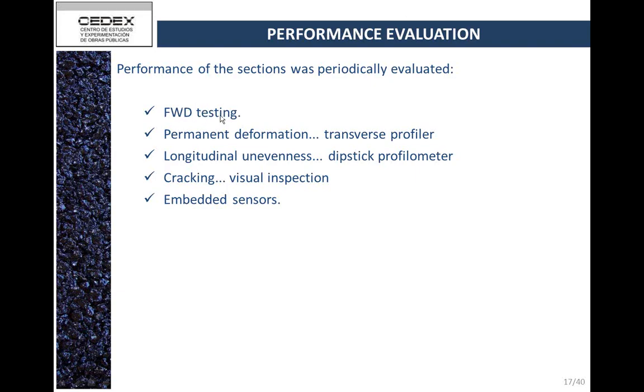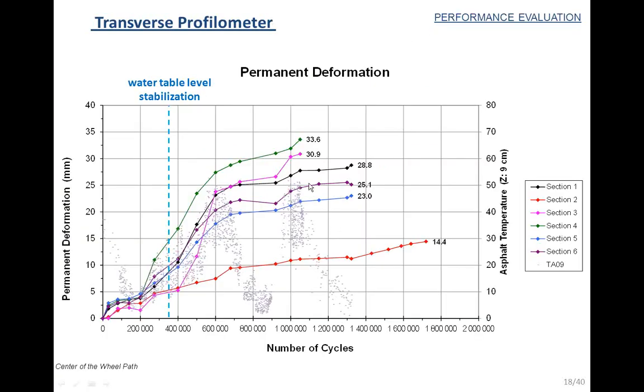Now, we also measure the performance in terms of different variables. We use FWD testing, as I have just presented, and we also use permanent deformation. We also measure longitudinal unevenness, cracking, and we also measure the performance from sensors. So, concerning the permanent deformation, here you see a graph for all of the sections, the 6 sections. You can see here the permanent deformation in millimeters, 25 millimeters could be 1 inch, and here the number of cycles. These blue points here correspond to asphalt temperature.